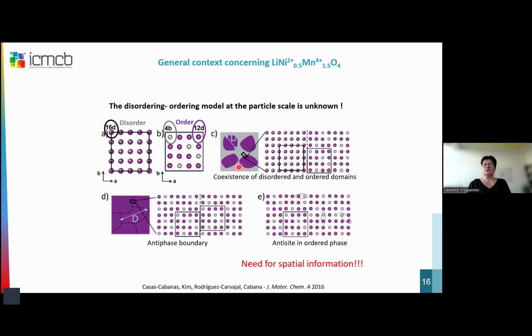But in fact, in the material, we don't know if it is a coexistence of ordered domains, more or less big, I would say, and next to them, disordered domains, or if it is much more subtle than that, with antiphase boundaries, as you can see here, or only anti-site defects, and I would say in that case, in the ordered phases, kind of punctual defects. So in order to have more information on that kind of disordered, ordered model, we need spatial information, and I will give you some clues about that in my talk.